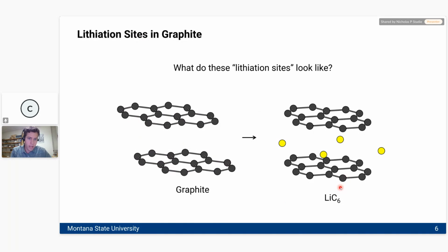And when we lithiate it to the maximum composition of lithium, we get a stoichiometry of LiC6, and it basically looks like this. The lithium slips in between the graphitic layers. I am showing you here a realistic depiction, to scale, of how much those layers need to widen in order to accept lithium in between them. It's not very much, and you can barely detect it by eye.